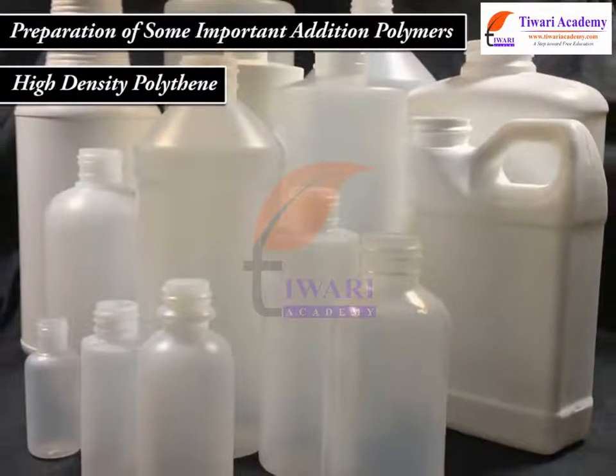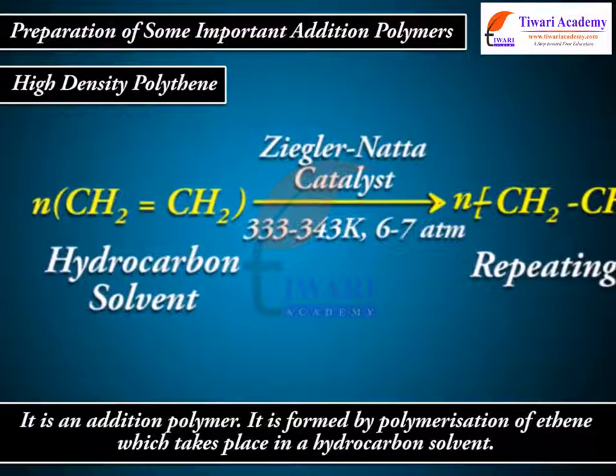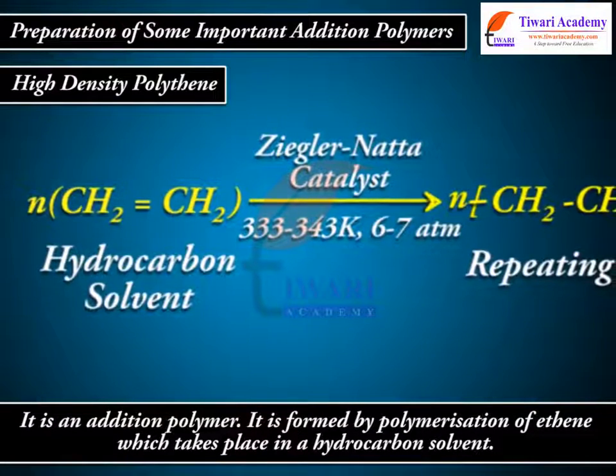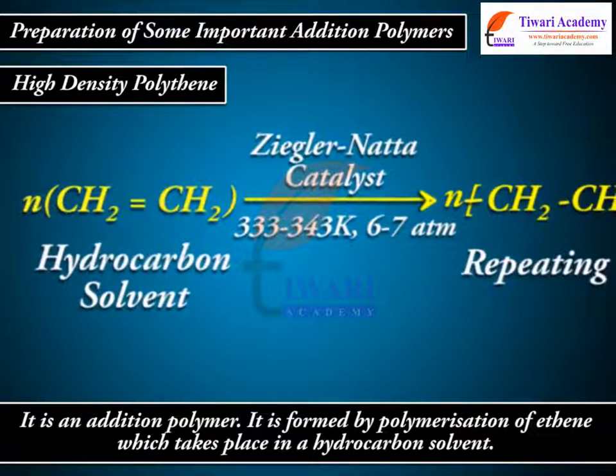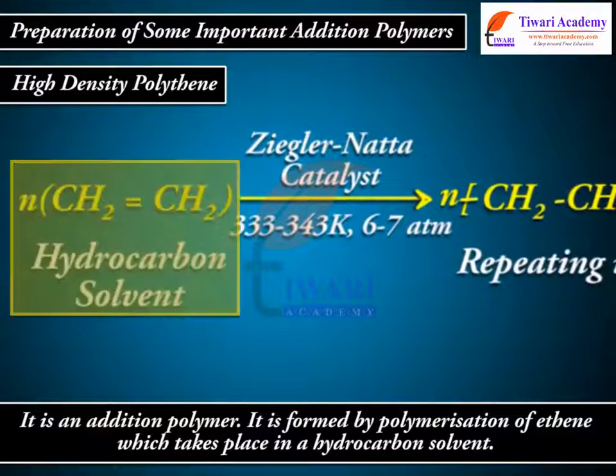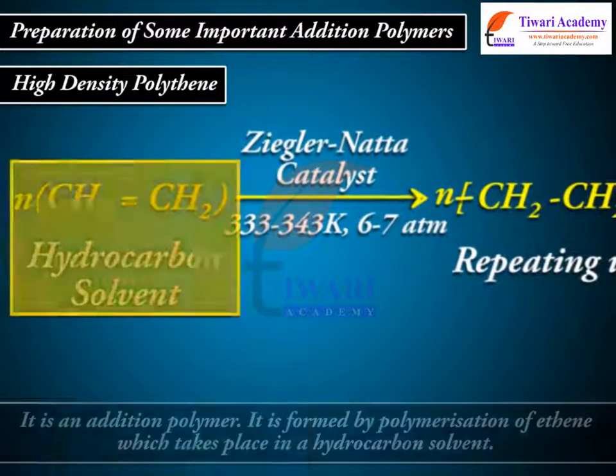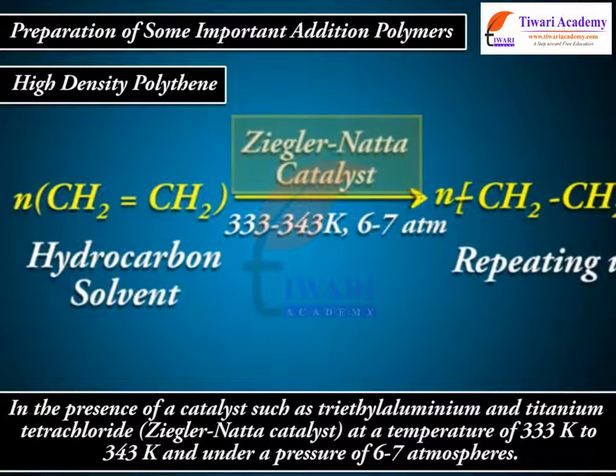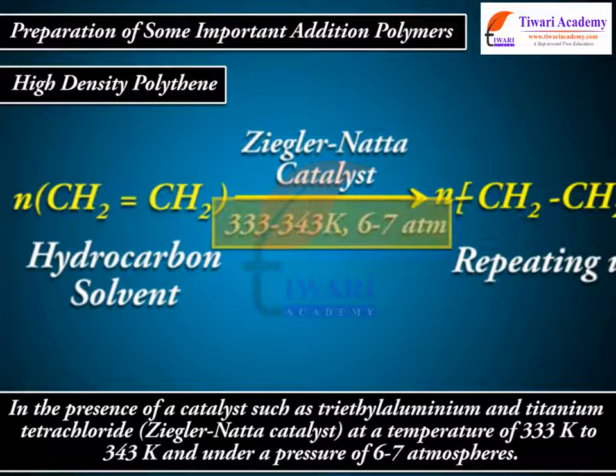High density polythene. It is an addition polymer. It is formed by polymerization of ethene, which takes place in a hydrocarbon solvent in the presence of a catalyst such as triethyl aluminum and titanium tetrachloride, Ziegler-Natta catalyst, at a temperature of 333 K to 343 K and under a pressure of 6 to 7 atmospheres.